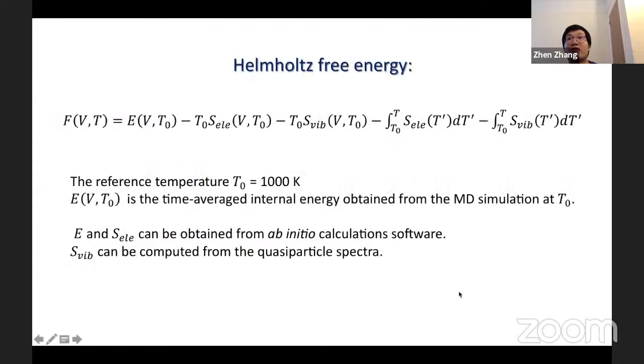As mentioned above, for calcium perovskite, we used the entropy integration to compute the free energy. Reference temperature T0 was chosen to be 1000 Kelvin. And the reference DFT energy is the time averaged internal energy obtained from MD at T0. Apart from vibrational entropy,